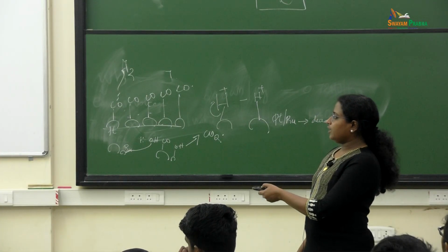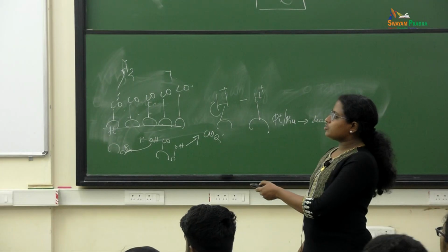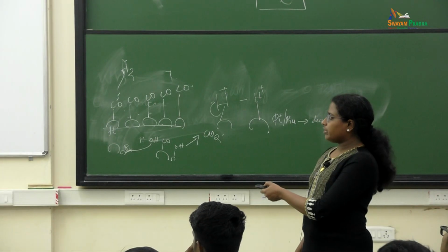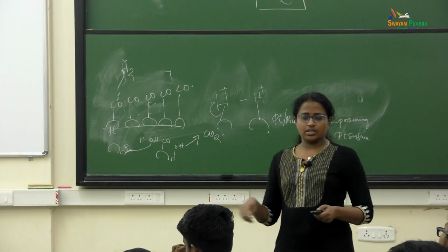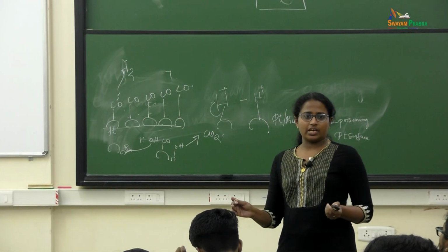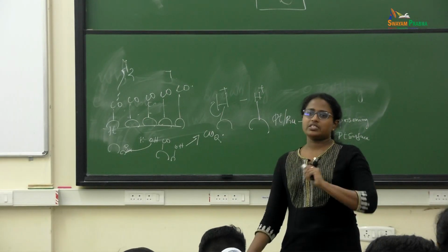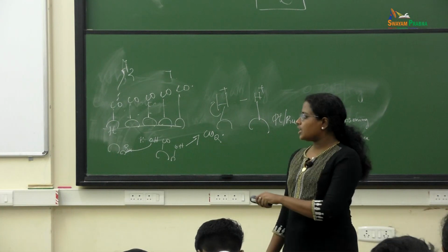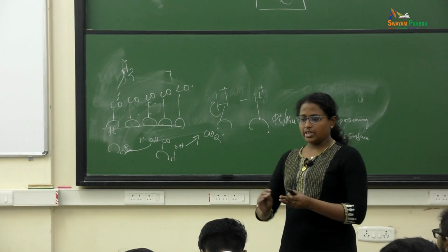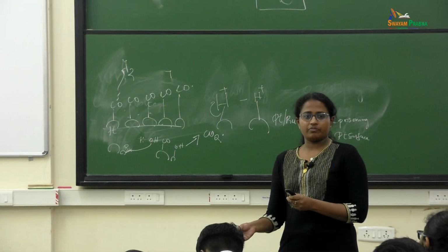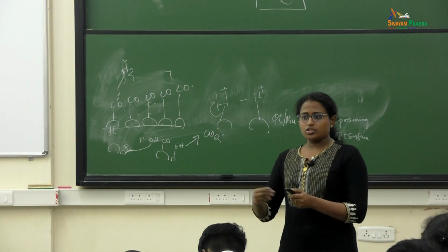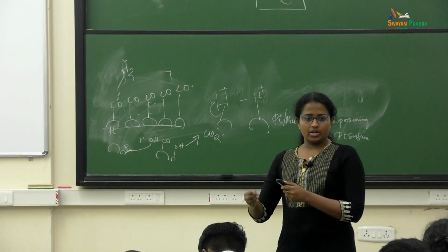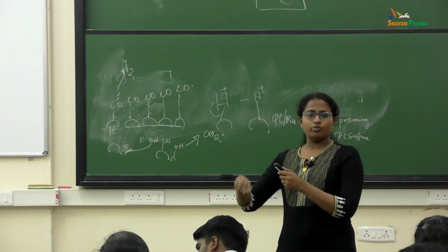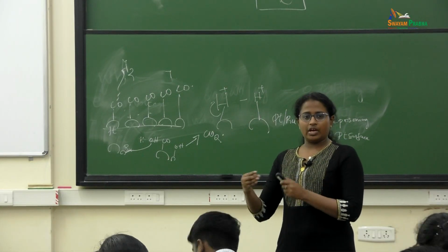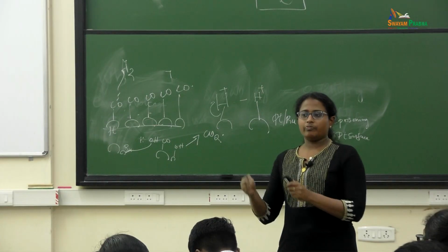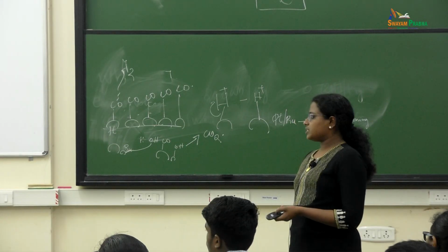So, again the stability of the catalyst is also an issue. For example, as I was telling, platinum is decorated on a carbon surface. This carbon surface gets oxidized during the process and the platinum gets dissolved from the carbon surface. Once the platinum gets dissolved from the surface, it goes to the membrane. It will start sticking onto the membrane, and you will have a lot of other unwanted backward reactions happening, and it will reduce the efficiency of your device.